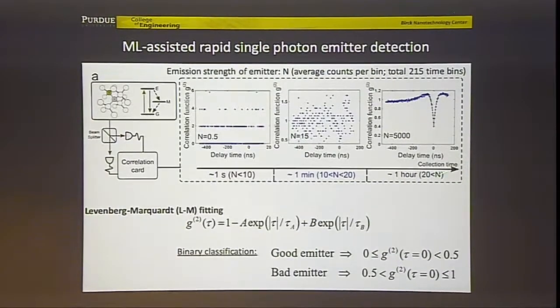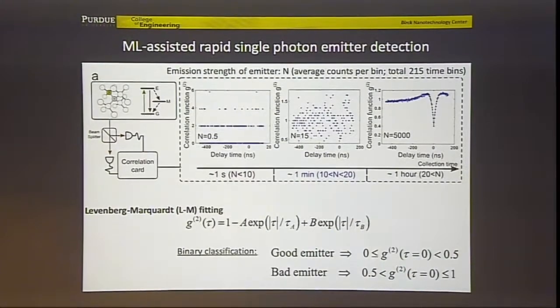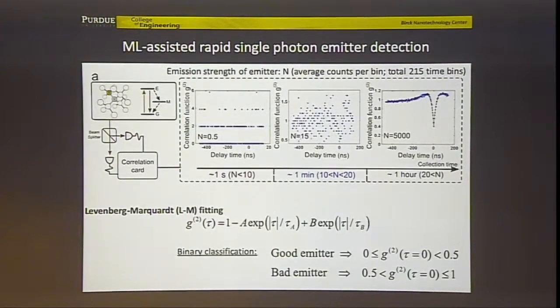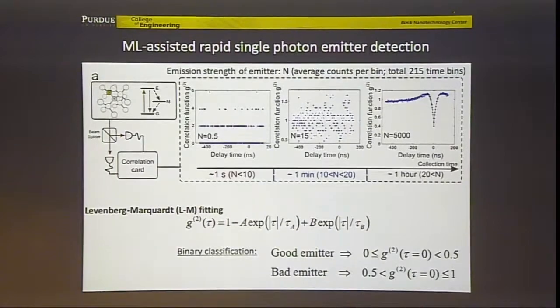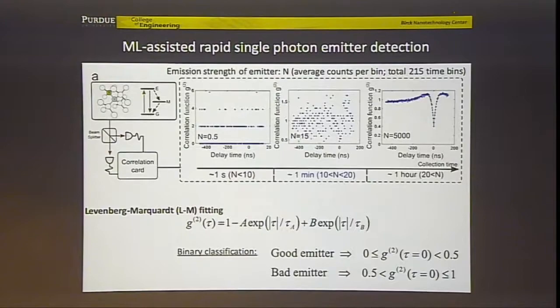If I use not many minutes of collection time, but let's say 1 minute, then that's how my spectrum looks. There is no way to fit any function like this. If you use a 1 second measurement, that's the way it looks. I mean, how could you possibly identify this function there? Machine learning. You take many emitters, you pre-characterize them by doing this stupid, long, time-consuming measurement, but then you train your neural network with many of them, and then the machine learns and will say with very high fidelity whether it's a single photon source or not. It's truly remarkable how it works.